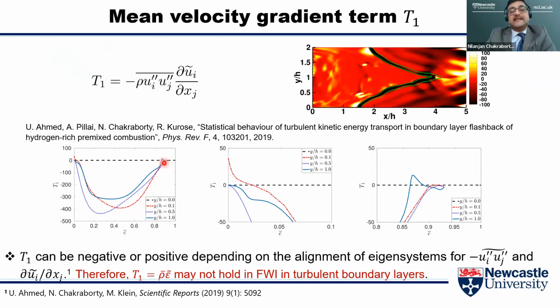So in other words, it doesn't work like a production term. It works like a sink to turbulent kinetic energy. As a result, the local equilibrium between the production and dissipation, which is often invoked in the non-reacting turbulent flow, falls completely in the case of flame wall interaction.